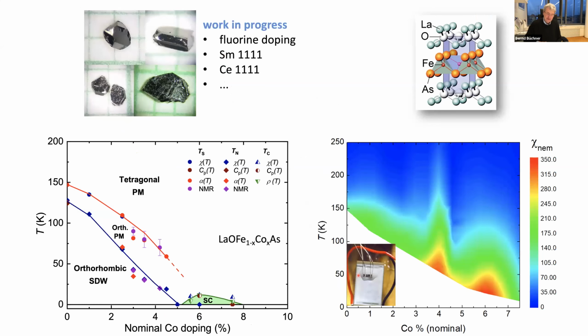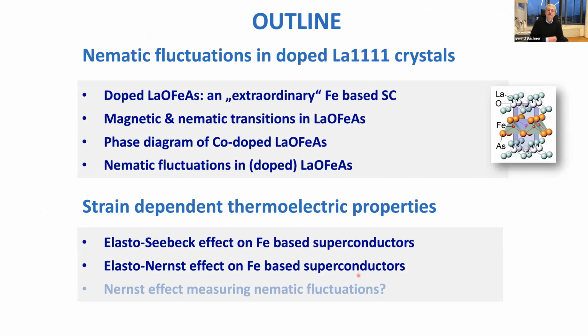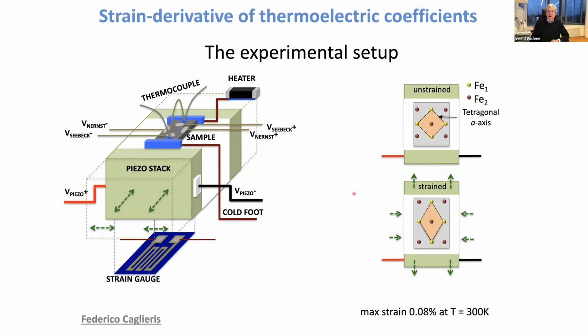Maybe I add a couple of transparencies on these thermoelectric properties, which give you even more information now that these systems are really very unusual metals. So what we are measuring now is we take again such a piezo stack. We take a sample, we apply a temperature gradient, and we measure the thermopower and the Nernst effect. And both of that now as a function of strain.